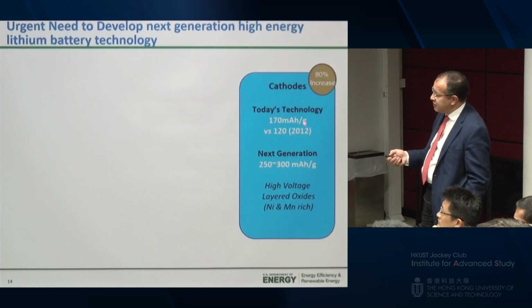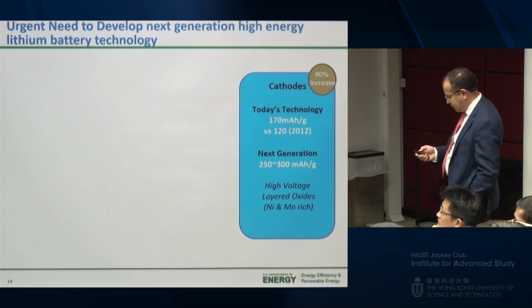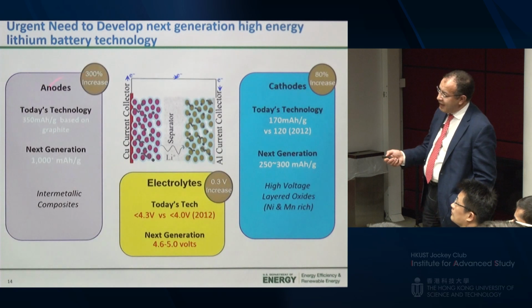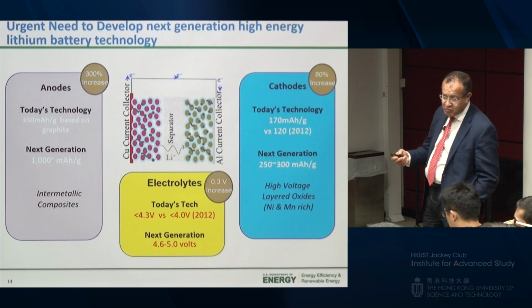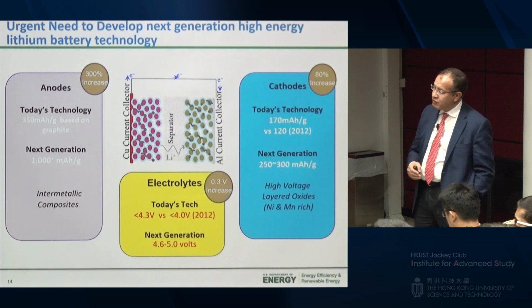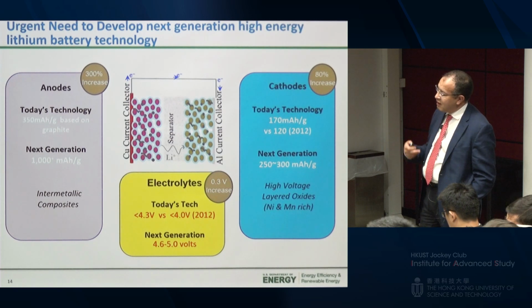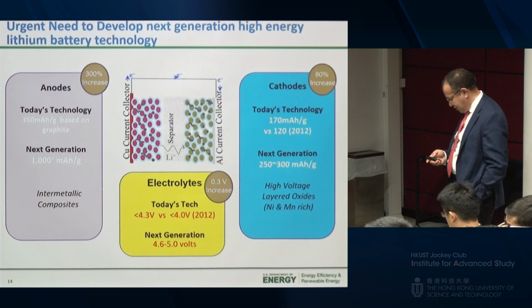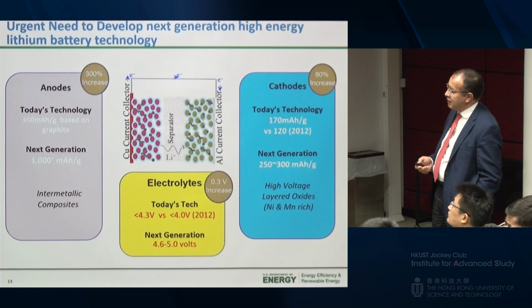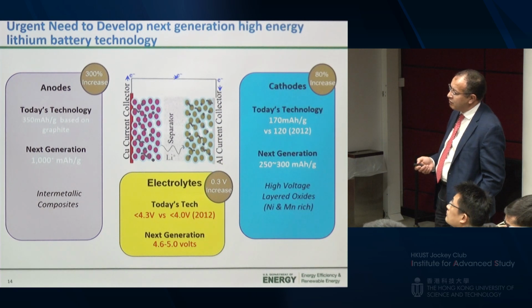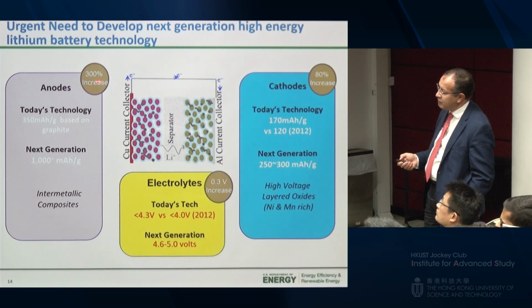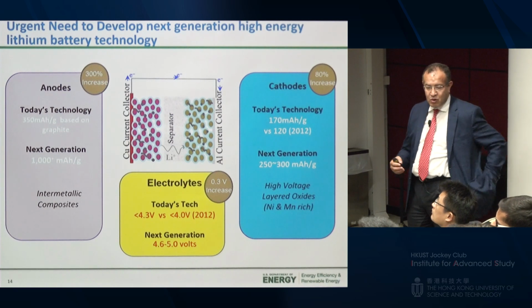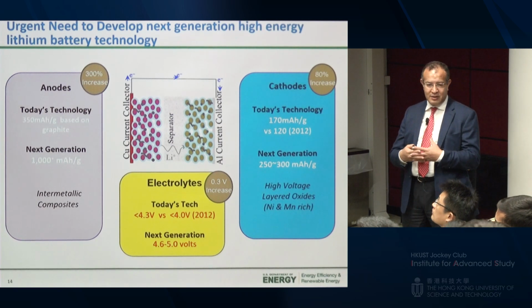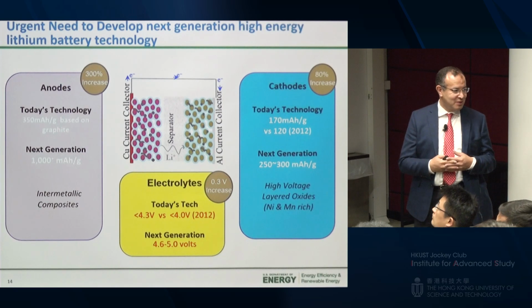You can do that by increasing the cathode capacity. These are the conventional capacities at the moment. Moving to this, basically increasing by 80%. You can do that with the anode as well. Now, moving from graphite, which has been the anode of choice for the past 30 years, there is a lot of effort now to move to metal or metal oxide-based, or intermetallic composite anodes. In that case, you have an opportunity of increasing the energy density by 300%. So by coupling these two systems, you can make a significant impact on the energy density of the full system.